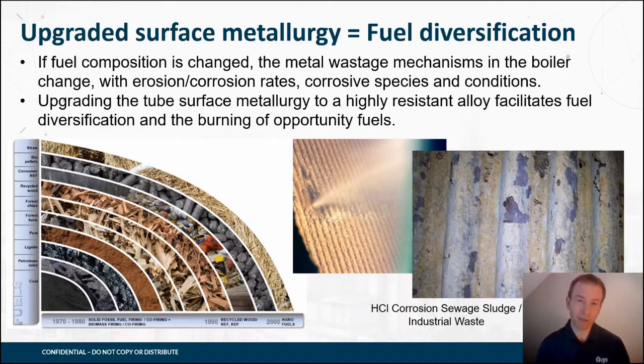The most common aspect of that's considered when we think about burning a biomass or a waste product, a recycled material or a reclaimed material, is an increase in chlorine. And that can come from many different sources, obviously from waste materials, from paints, from materials that have been recycled, etc. That chlorine gets into the combustion environment and can create a very different and much more aggressive corrosive attack to the water walls, ultimately leading to localized pitting and then failure of the water walls, leading to unplanned shutdowns of the unit. So upgrading the tube surface metallurgy to an alloy which is resistant to those environments facilitates that change and that diversification in the burning of different fuels, and also switching during the operation of the boiler in between outages without having to carry out another change, switching between different opportunity fuels, which can be dependent upon availability, dependent upon cost in the marketplace, etc.